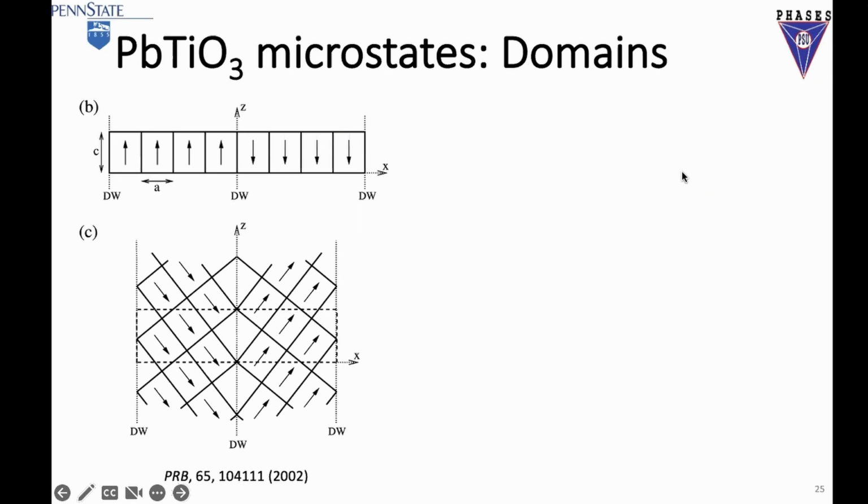For example, if two spins head to head, it is unstable; tail to tail is unstable. But you either have 180 degrees stable or 90 degrees stable. All other ones are not stable. That's good. So they calculated the energy of these two. So then I thought, gee, now we have two states, then we have three states, right? We have the purely ferroelectric state without domain walls. Then you have the 90 degree with domain walls, and 180 degrees with domain walls.